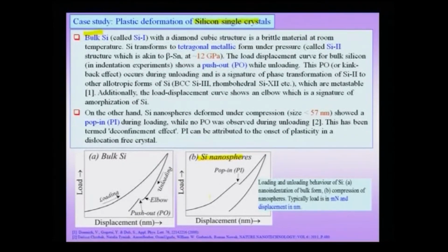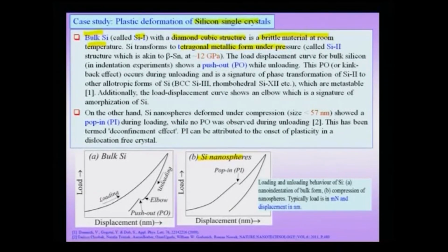Bulk silicon, which is typically called silicon 1, has a diamond cubic structure, and we know it is a brittle material at room temperature. It actually transforms to a tetragonal structure under high pressure, which is what is experienced under a diamond indenter, and this tetragonal structure, which is a metallic form, is called silicon 2.